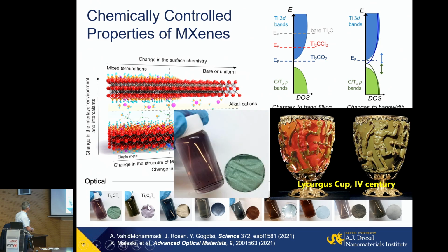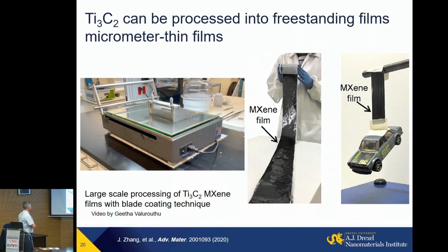But titanium 3 carbon 2 is exactly the same, and you can actually tune this color by changes of its chemistry or tune it electrochromically, green in reflection, red in transmission, with a difference. There is no gold here. This is just cheap titanium and carbon inside with oxygen termination. So we have all this array of properties that we can tune and control. Now, what do we do with these materials? I think I'm running out of time. I have about 20 minutes left, so let me show you a few things. First, we can very easily process them.